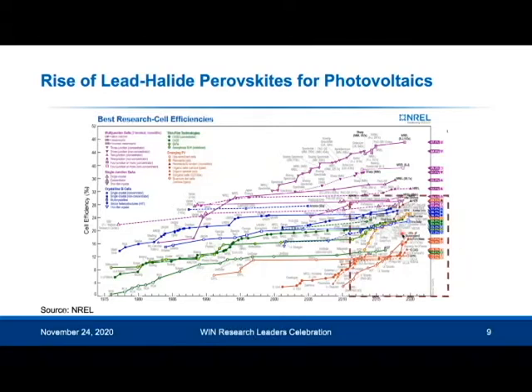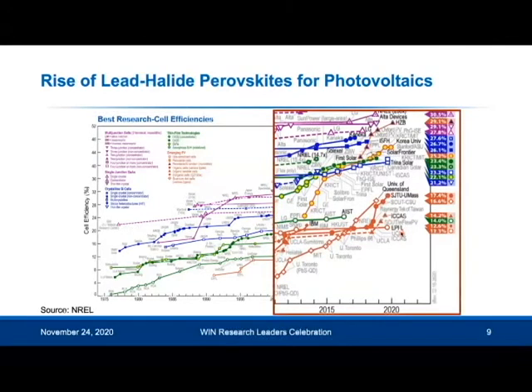So let's zoom in into these. And you can see that one of the fastest growing new technologies is represented by these yellow circles here. And these are the lead-halide perovskite solar cells. These are based on polycrystalline thin films. And even though they've been developed for just 1 decade, these are already more efficient than multicrystalline silicon solar cells. And they're in fact almost as efficient as the best single crystalline silicon devices. So that's quite remarkable. You can also have these perovskites work in tandem, in conjunction with silicon solar cells.